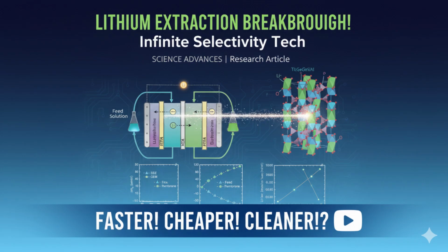They sit on the surface, potentially blocking the active sites where lithium needs to enter the lattice to begin its journey. So higher concentrations of sodium or magnesium in the feed solution lead to a lower lithium flux, even though the selectivity remains perfect. That makes sense.